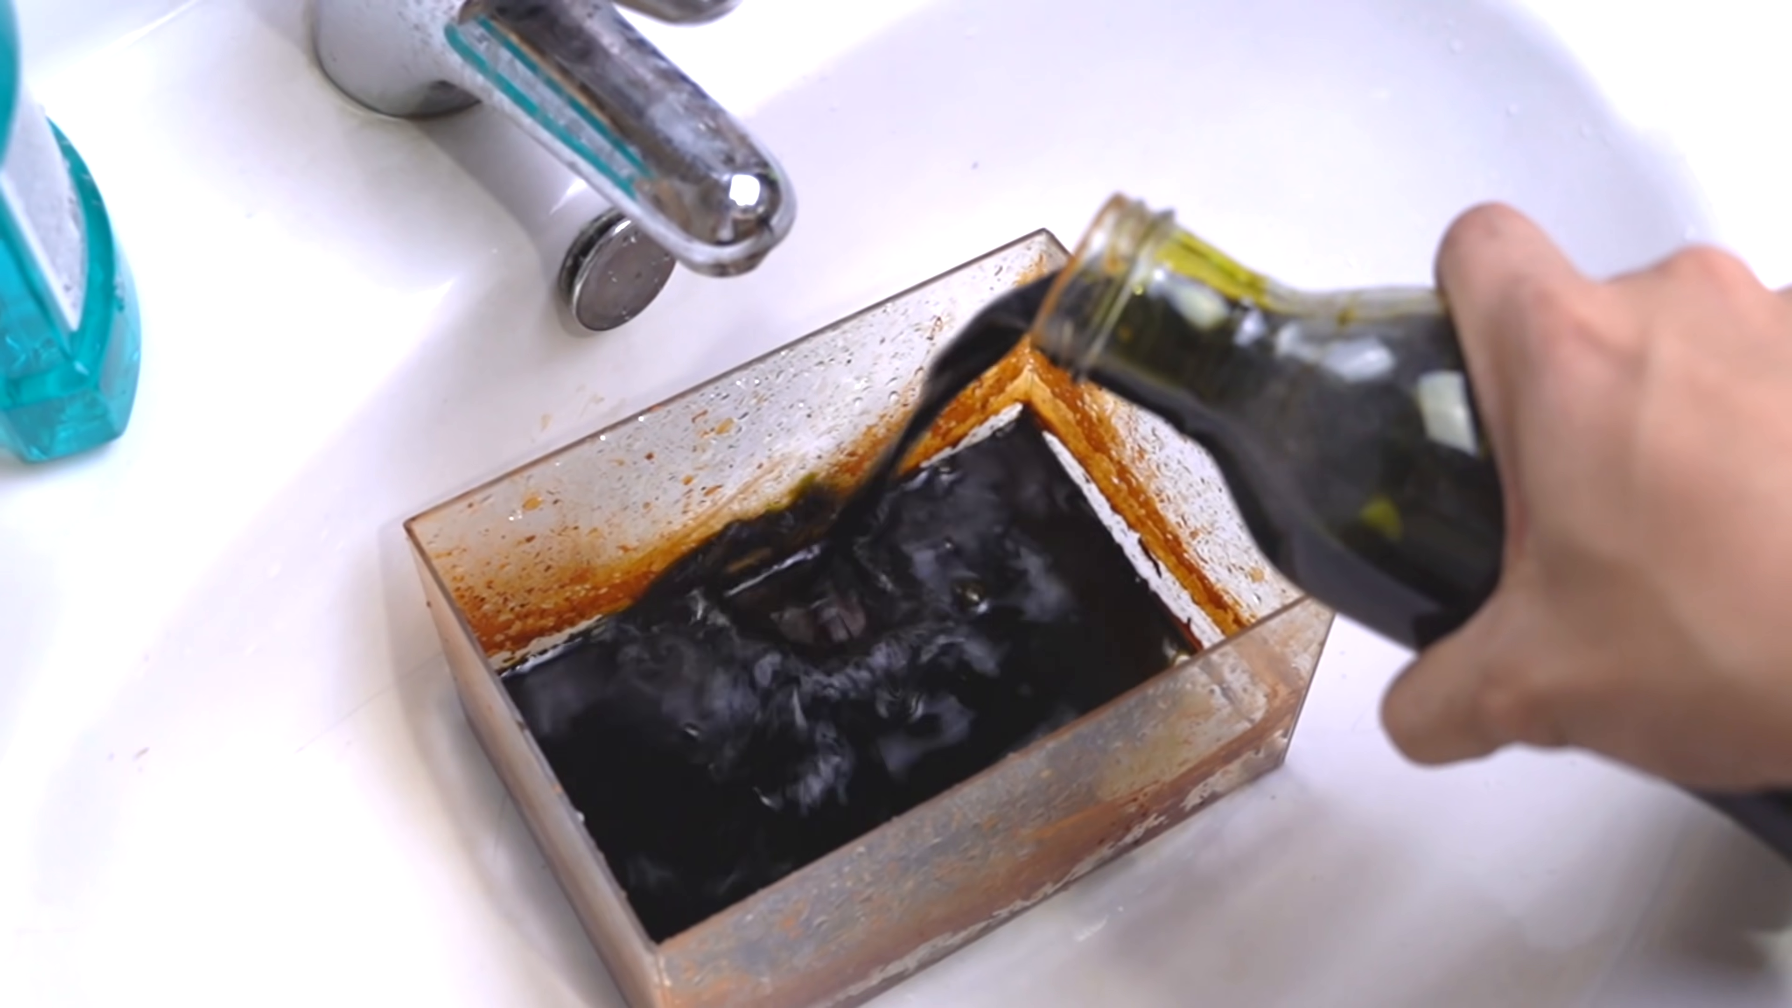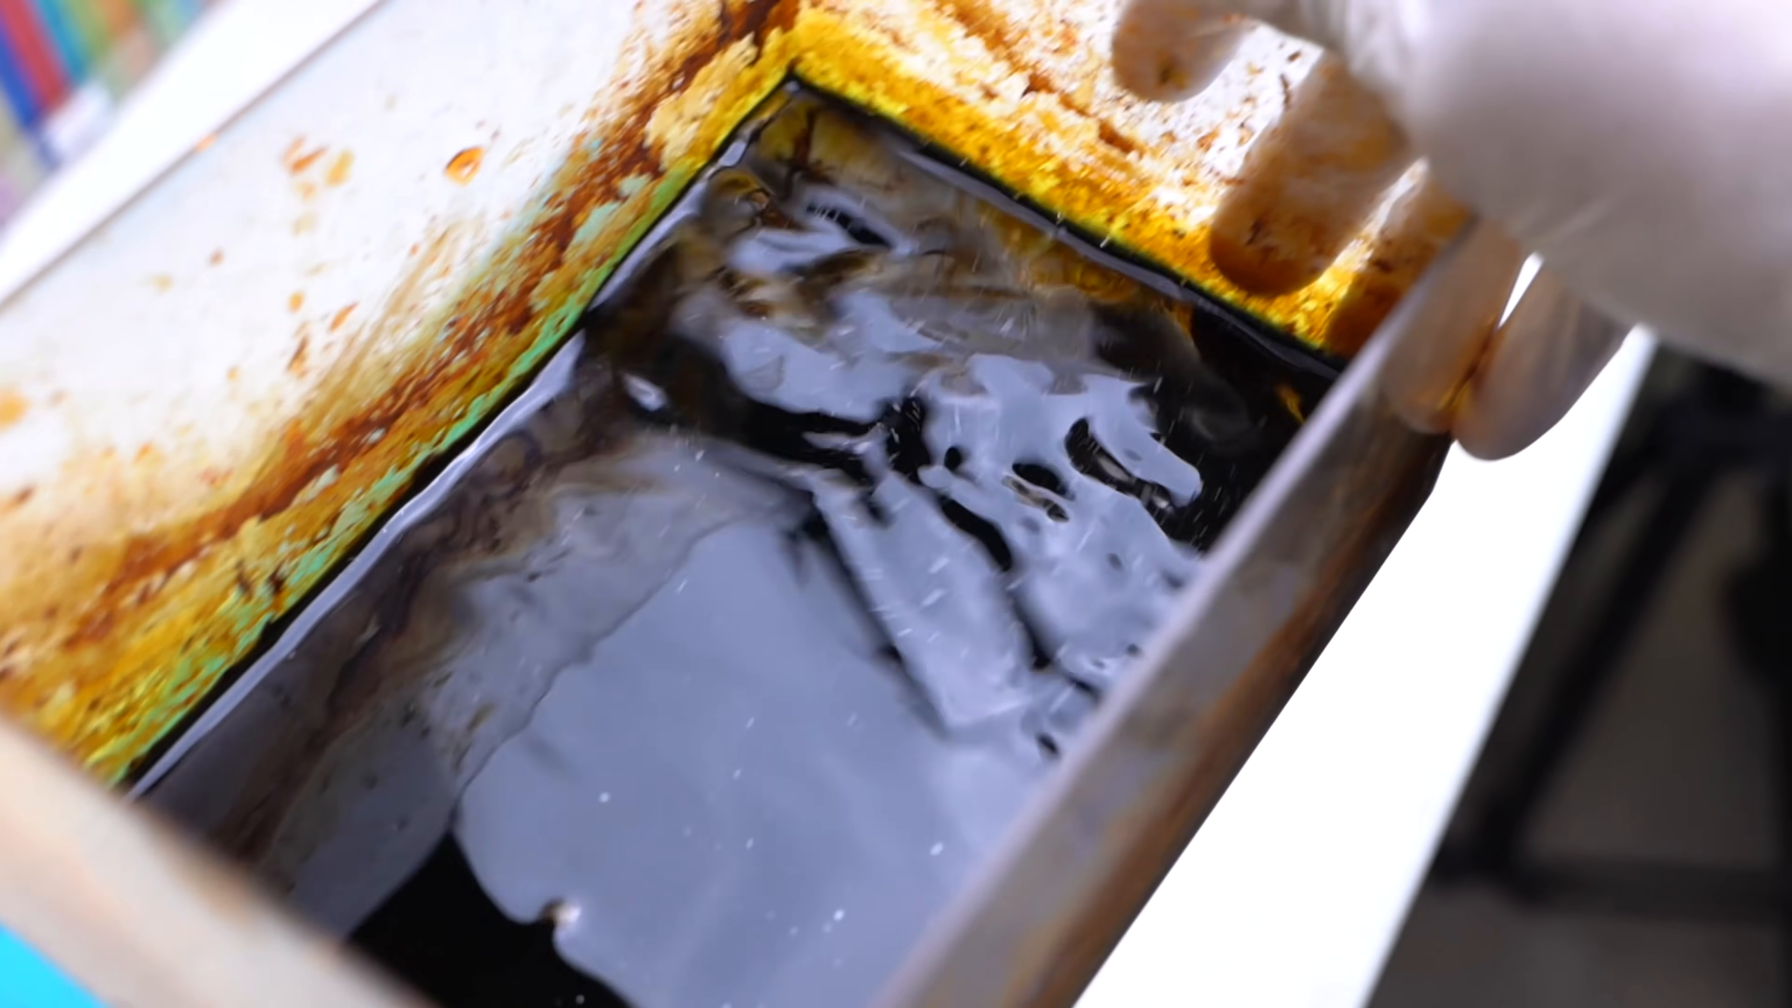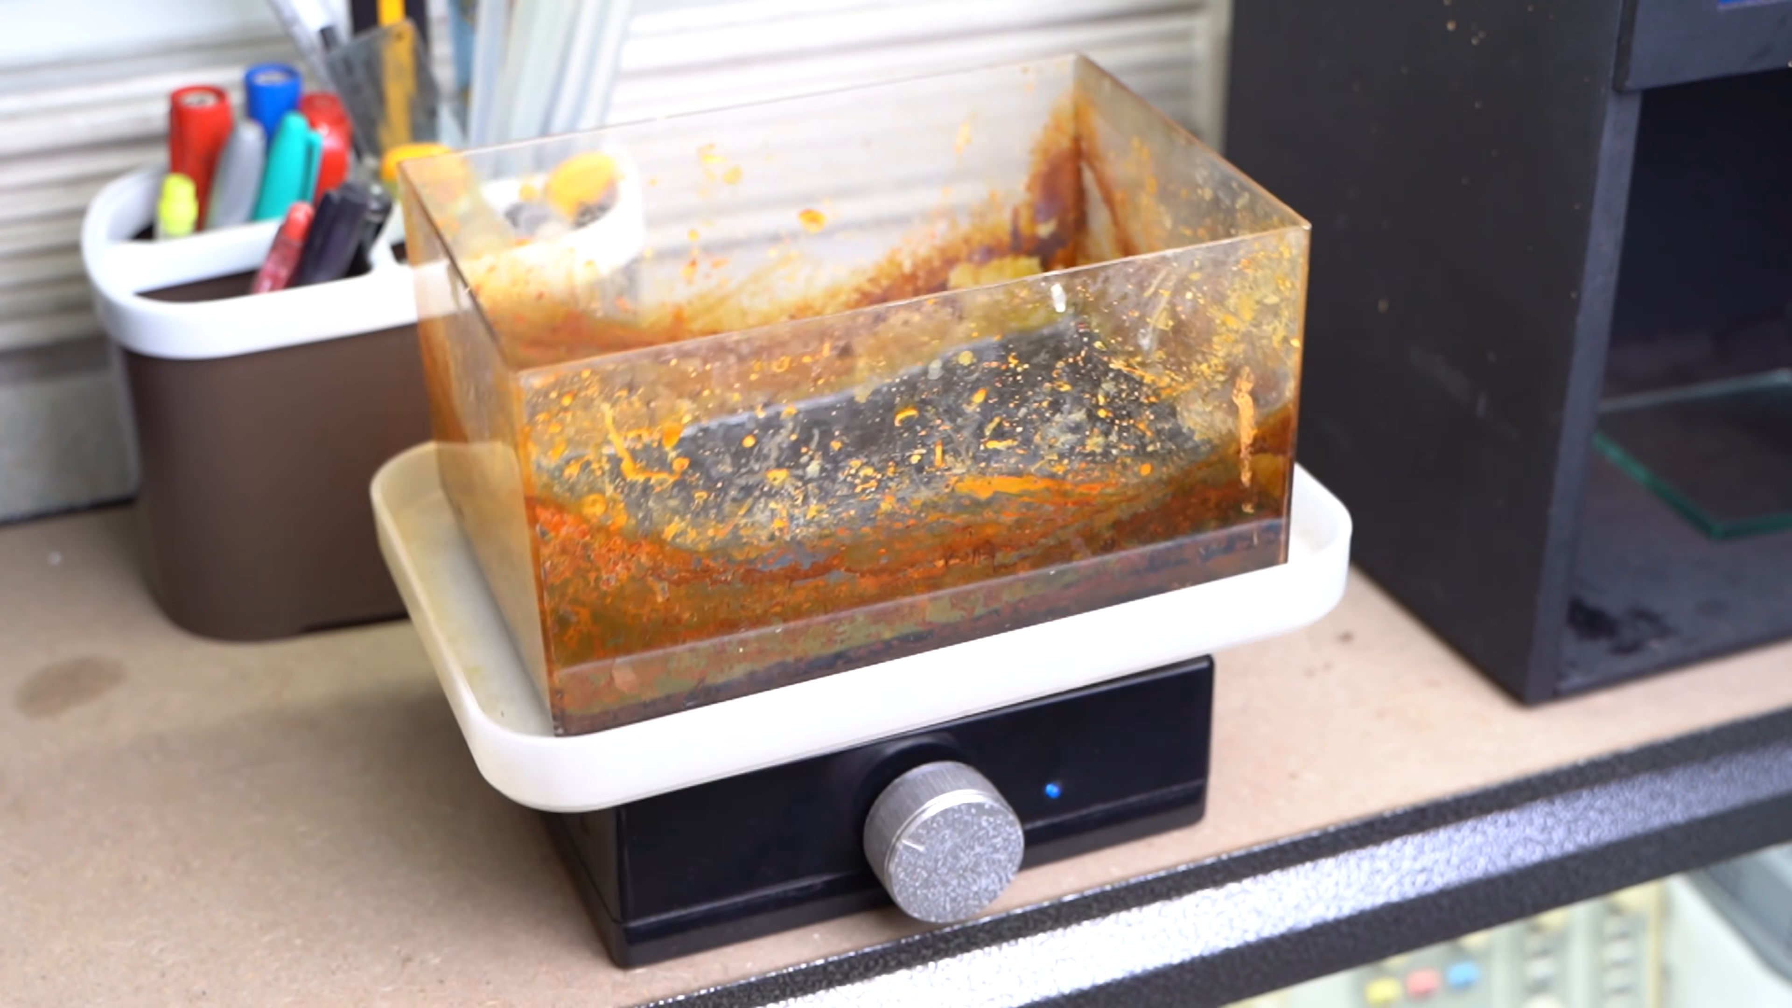When you're done, you can grab your etching solution. I'm using ferric chloride, the most common PCB etchant. Place your board on the etchant and agitate the tray for around 10 to 15 minutes until the unmasked lines are dissolved. I don't have the patience for that so I made a do-it-yourself etching machine. Feel free to check out my tutorial about it.